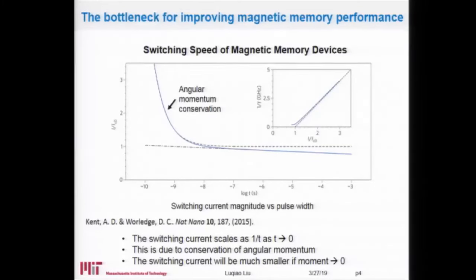However, although this is governed by the fundamental law of angular momentum conservation, you can also imagine that if the magnetic layer itself does not carry too much angular momentum to start with, then you can make it faster. Yes? So that's for one electron spin? This is for all of the spin ensembles inside the magnetic layer. Yes, so you apply this much current and then switch all of the spins together in the magnetic layer.